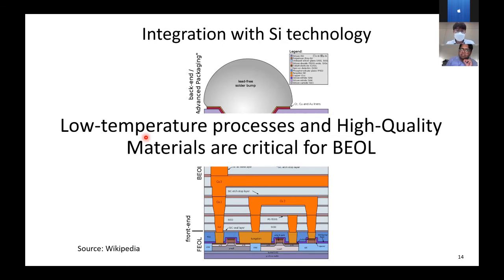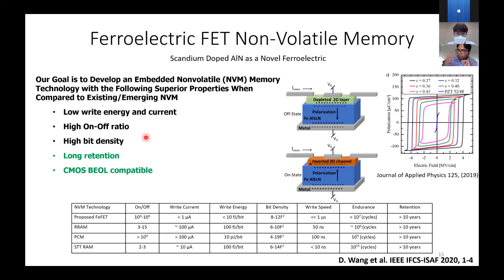This is not easy. But we have been fortunate in finding one such material which can be deposited at low temperatures, and that is also ferroelectric in nature. And this material is scandium doped aluminum nitride. This was discovered in 2019, so it's a very new material, right? This combined with 2D material, and the advantage of 2D material is it can be transferred at room temperature on any material you want by wafer bonding, you can now think about a low temperature back end of the line compatible assembled high performance memory device.